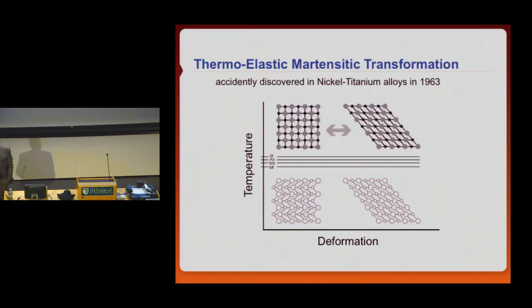Nitinol is by far the most important shape memory alloy in the market today. It's actually the only one that made it to commercial applications. The copper-based alloys, we tried that in the early 70s. They are not corrosion resistant, particularly stress corrosion cracking happens a lot. They are not stable, and for medical applications, they wouldn't be used anyway because they are not biocompatible. So Nitinol has an ideal combination of properties.